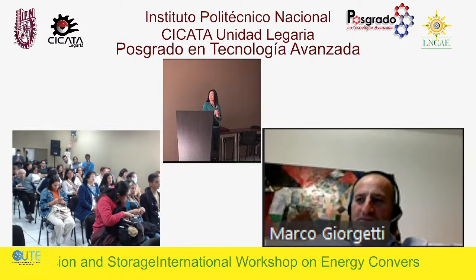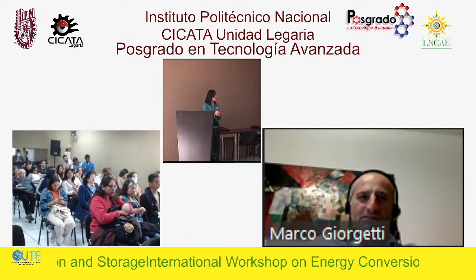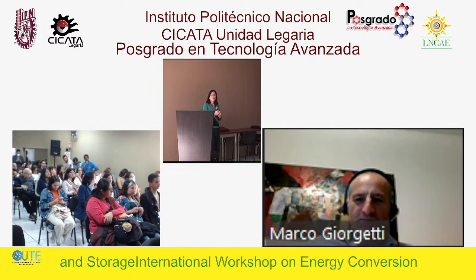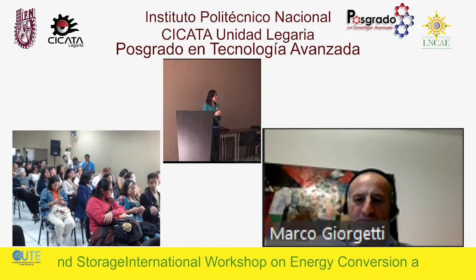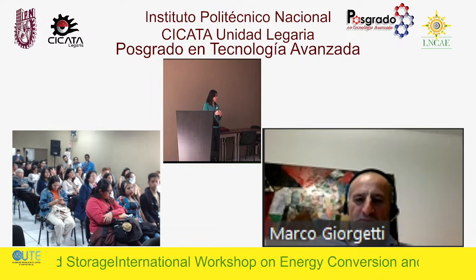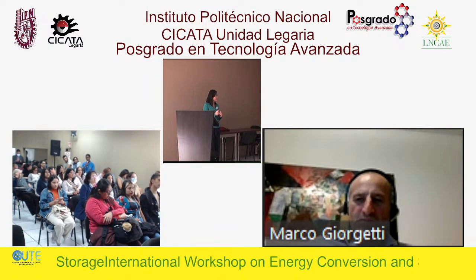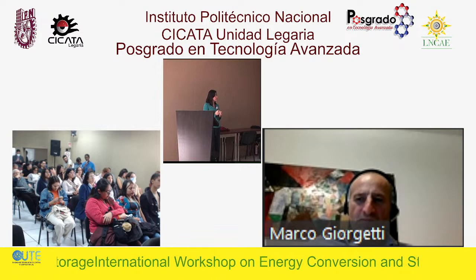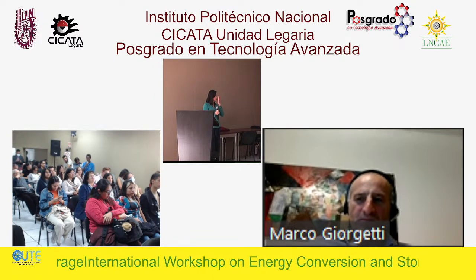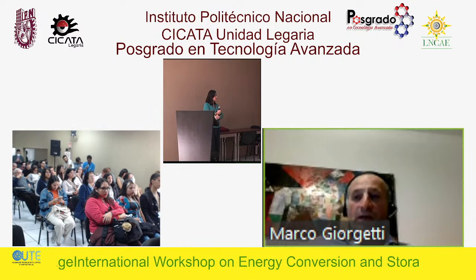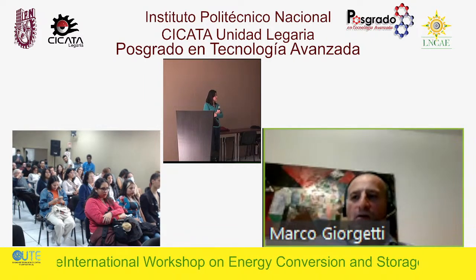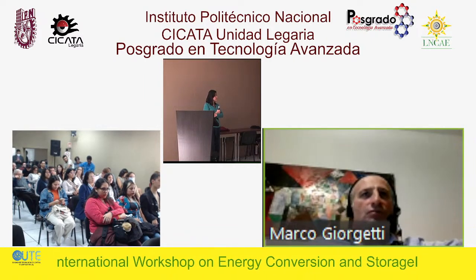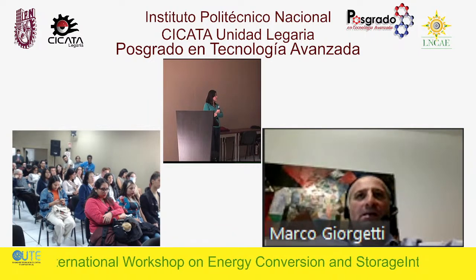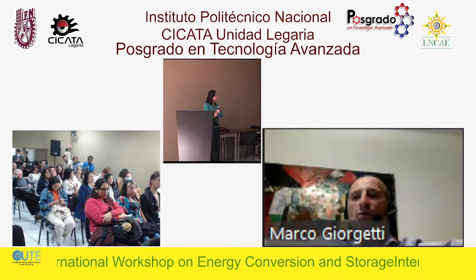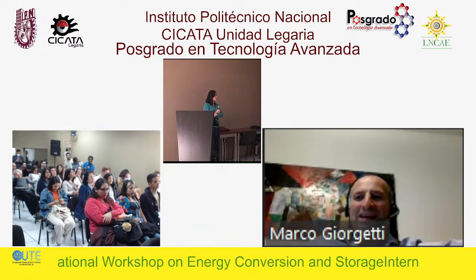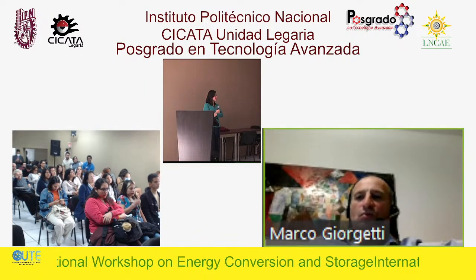It was very interesting. I was wondering, what is the biggest challenge when you are studying the insertion of ions such as lithium and sodium, which are very small, by XRD, by X-ray diffraction? By XRD, okay. If you go to a synchrotron and you have a very crystalline material, sometimes when you do Rietveld refinement, you can also try to analyze the deposition, so you can have a clue.